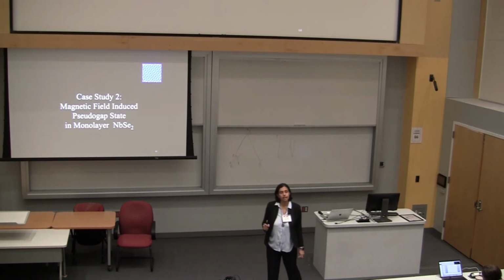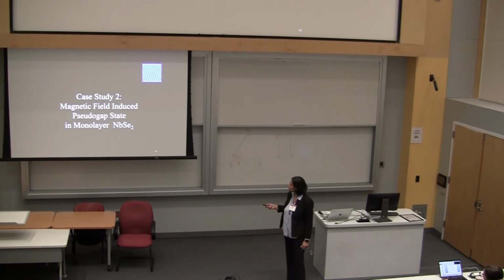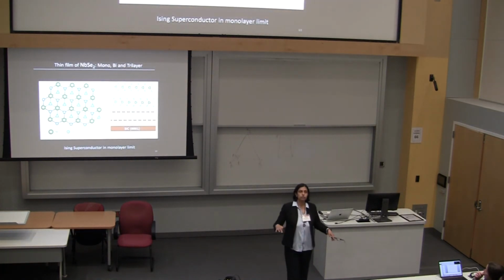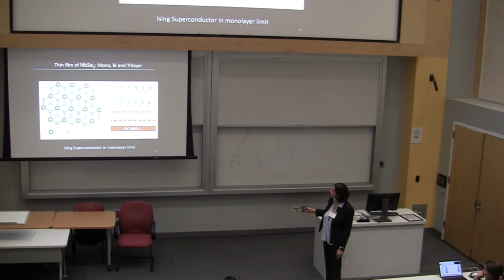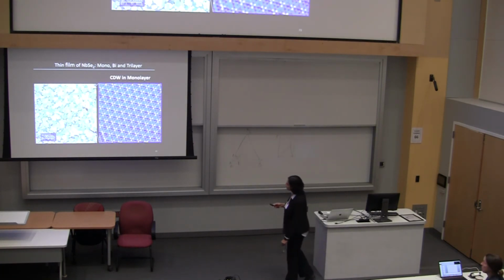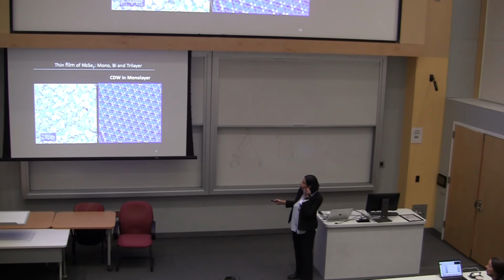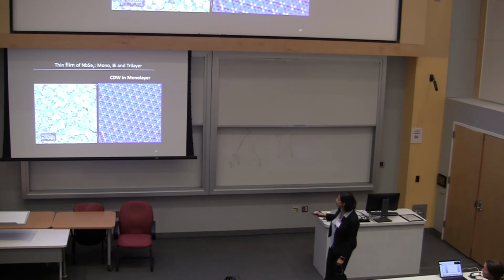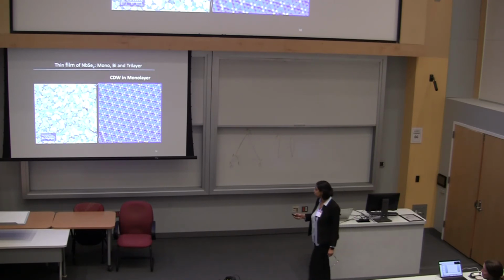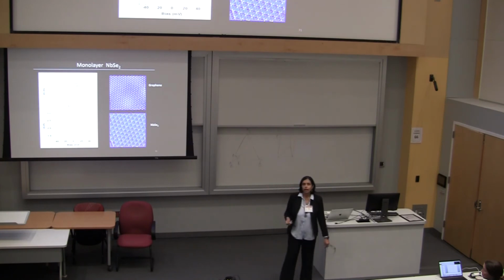on monolayer niobium diselenide. We were very interested in niobium diselenide because it remains superconducting down to the monolayer limit. We grew 2 layers of graphene, bilayer graphene, on silicon carbide, and then we grew either 1 or 2 or 3 layers of niobium diselenide. And we measured the material spectroscopically using STM. So this is what it looks like on very large length scales. And if you zoom in, in most places you can actually see the CDW. This triangular arrangement of atoms, this periodic arrangement, that's actually the charge density wave in niobium diselenide.